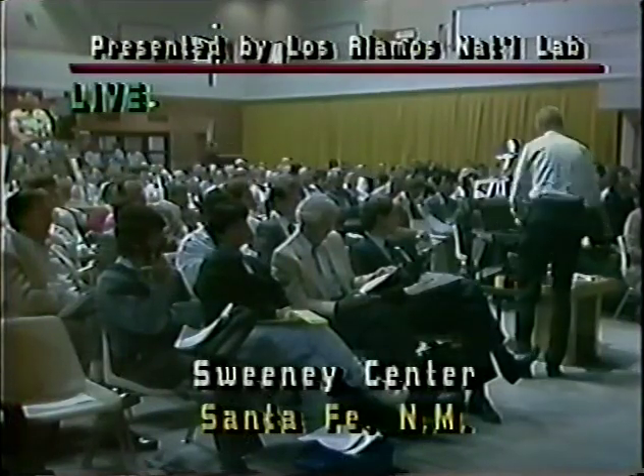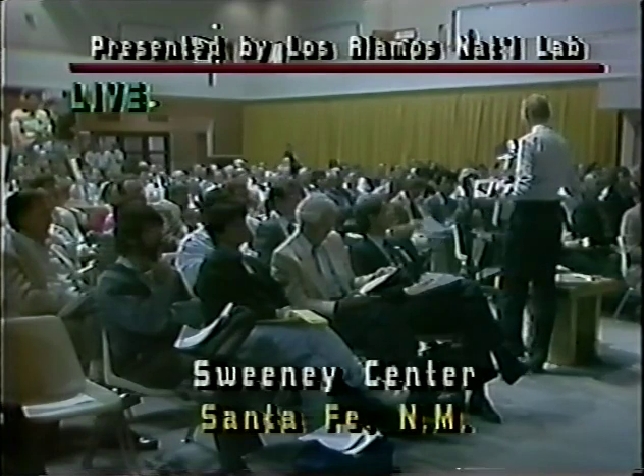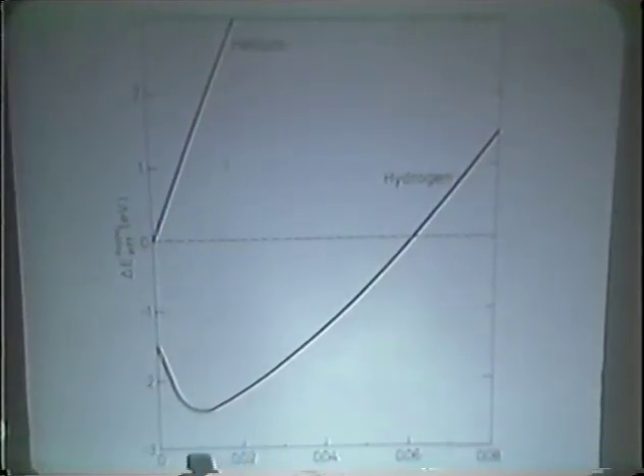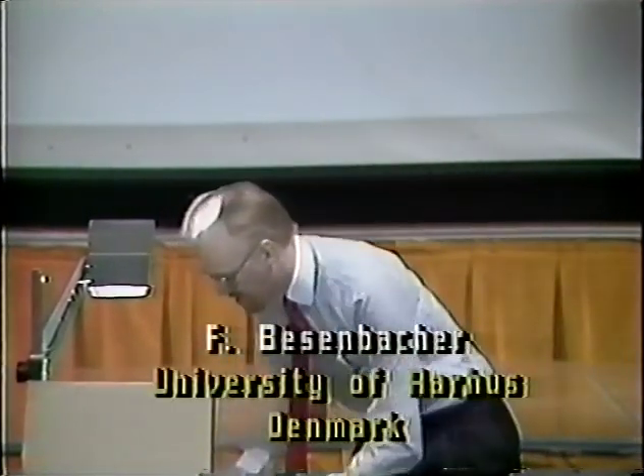And for example, if you look at chemisorption of hydrogen outside a metal surface, you would say here in principle that every hydrogen outside a metal surface can find a position corresponding to this minimum here, and then you would have the same chemisorption energy for all the metals. That's of course not true. But we also had the other term down here, which was proportional to 1 minus f. So if you now plot the chemisorption energy, experiment and theory, then you see that the chemisorption energy increases to the left in the transition metal series. And there's a very good agreement between experiment and theory. And this increase to the left is nothing else than this 1 minus f down here. Also, the heats of solution are very nicely reproduced by this theory here.